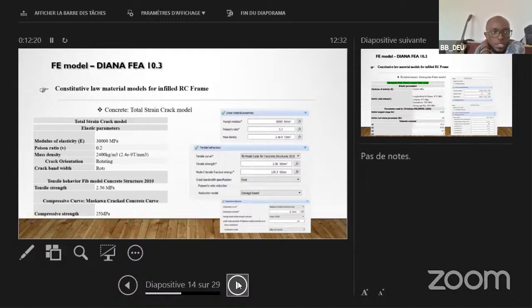That describes the concrete: modulus of elasticity, Poisson ratio, mass density. For crack orientation, we take rotating. For crack bandwidth, we use the literature for rods. For the tensile curve, we use the fib Model Code concrete structure code, and the tensile strength is defined. And for the compressive curve, to define a hysteretic curve, we use the Maekawa cracked concrete curve. Also, we define the compressive strength, which is 25 megapascal. So here we illustrate the parameters of DIANA.